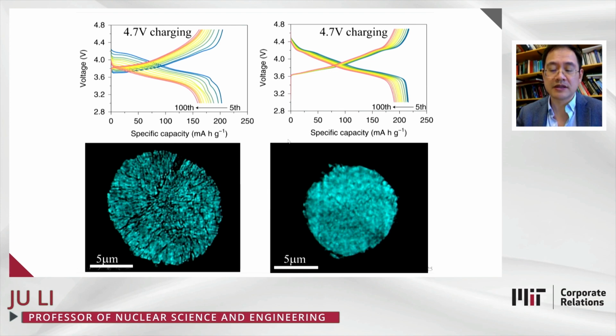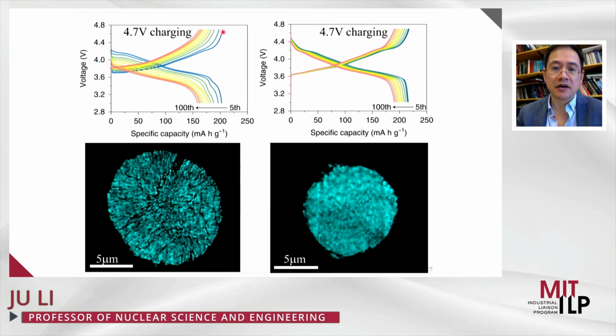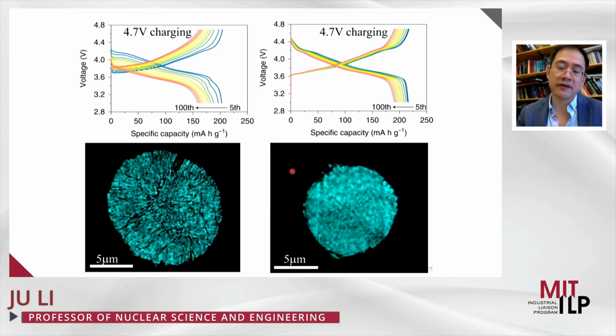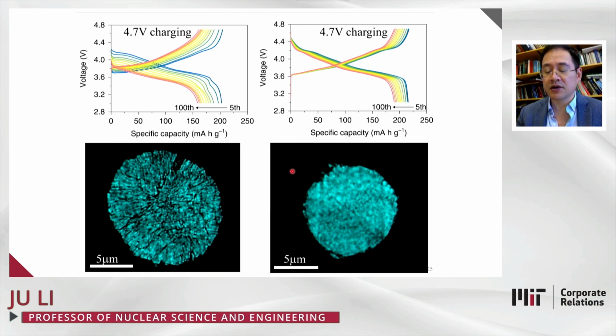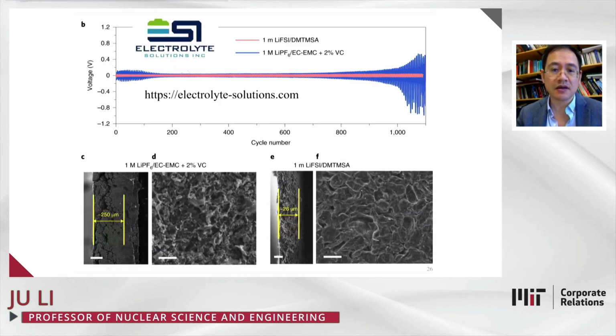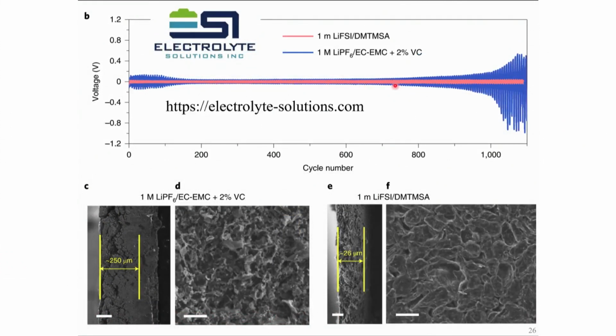So here we show that with this new electrolyte, we can charge to extremely high voltage and get much higher energy density, but without the stress corrosion cracking and dissolution of the NCM 811 secondary particle, which is a polycrystal and tends to crack along the grain boundaries. But just by changing the electrolyte, with everything else, the loading, the charging policy, the temperature, the cycle, all the same, we can effectively suppress the cracking of the cathode and prolong the cycle life of the battery. So now there is a startup company called Electrolyte Solutions, which is trying to mass market this new electrolyte system.